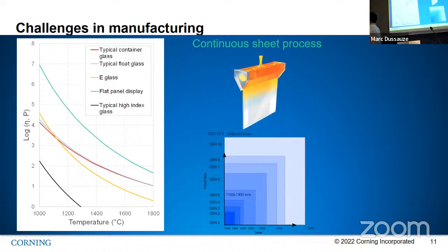So you see that in the 90s, we were at Gen 1, Gen 2. The dimensions were pretty small, and now we are at Gen 10.5. You are at 2940 millimeters by 3370 millimeters. So it's becoming very big, and that's key to enable mass production, basically, to cut down on cost. And so you see that once you have the glass composition, you really need to have the right process to make it, to go to mass market.